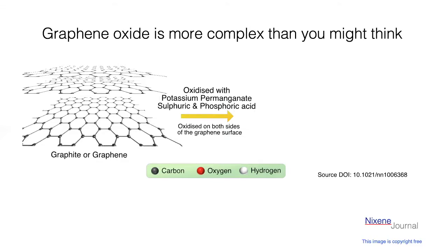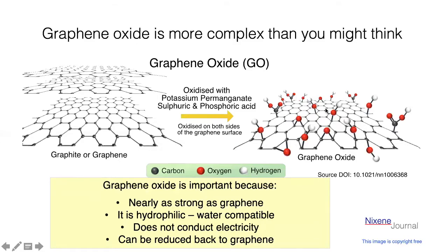Graphene is a very stable material. So this is concentrated acids, concentrated potassium permanganate, which is an oxidizing agent. When you expose graphene and graphite to these conditions, what happens is the chemicals split the different layers apart — it turns graphite into graphene just by the chemistry of the reactions. So it does what's called exfoliation — it takes the individual sheets of graphene and tears them apart chemically from the graphite. Then all these different groups get stuck onto the surface of the graphene, and that makes graphene oxide.